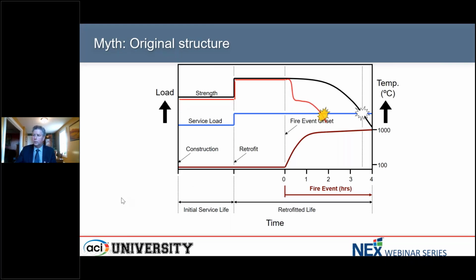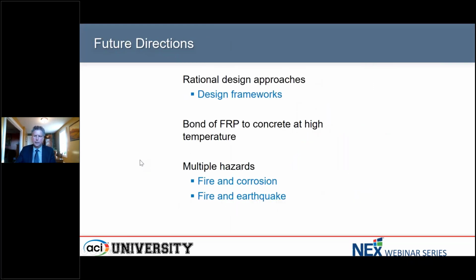Now, what happens if you don't provide any insulation is we have a very similar situation. You increase, we have a similar service load at this point, but you don't provide insulation. So what happens is we lose a lot of strength of the FRP very early on, and then you don't have as much reserve for the other members. So we do start to lose strength gradually for the remaining reinforced concrete structure, but then we have failure at a much earlier time than we would have had before. And that's exactly what we observed in some of those tests on the columns.